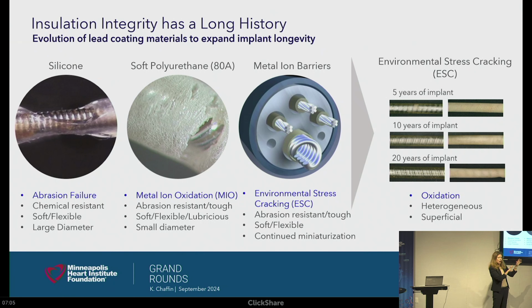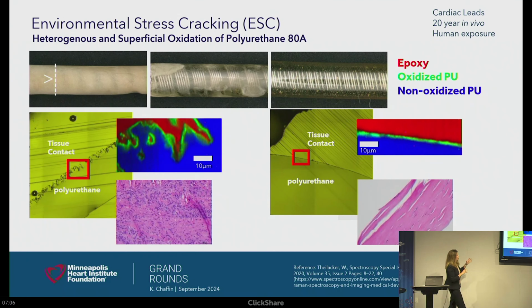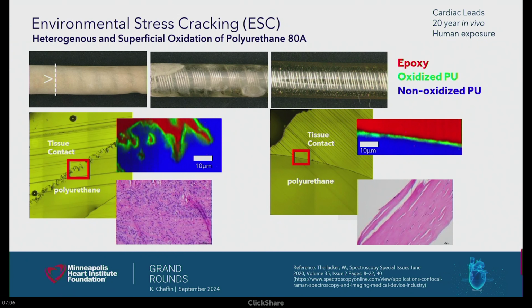But we have gone back into our treasure trove of return cardiac leads. And I'm just showing you some pictures to understand that environmental stress cracking, or that whitening that you often see on a lead when you explant it from a human. And what we discovered are two things. First, when we took a collection of leads that have been exposed for 5 years in the body, 10 years in the body, and 20 years in the body, we could find parts of the lead that looked pristine. And other parts had this opaque white look. And we were really curious about that. And we went deeper. And this transition between white and pristine can happen very, very abruptly. And you find places like that picture in the middle where it's very heterogeneous.